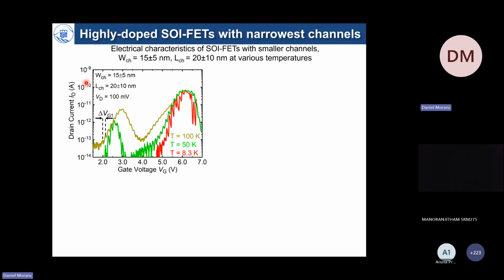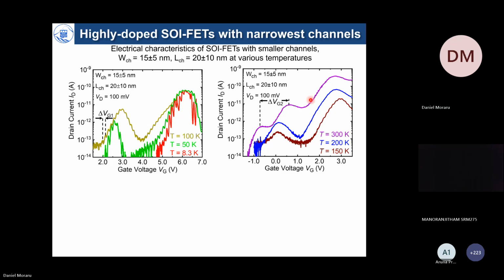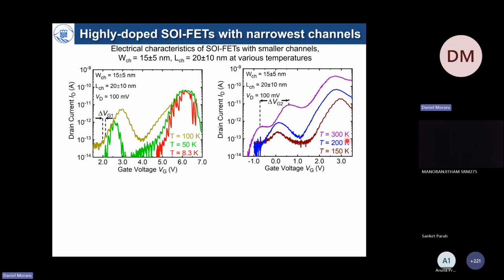I'm showing here drain current versus gate voltage at different low temperatures first. You can see that there are broader current peaks and very fine current peaks superimposed on each other. The reason for this is that we are dealing with two different quantum dots working in parallel. But what is the most important is what happens at high temperatures. Even at 300 Kelvin, we can still observe very prominent current peaks, which are an illustration of survival of SET operation even at these high temperatures.